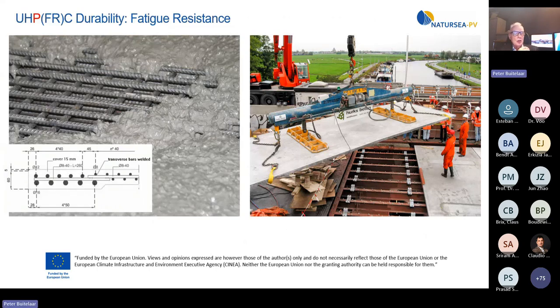Durability is also resistance against fatigue. For the replacement of a 150 mm thick wooden deck on a basculebridge in a highway with prefabricated ultra-thin hybrid reinforced UHPC with a cover of only 10 to 15 mm on the reinforcement, several additional tests were required by the Ministry of Infrastructure and Water Management.